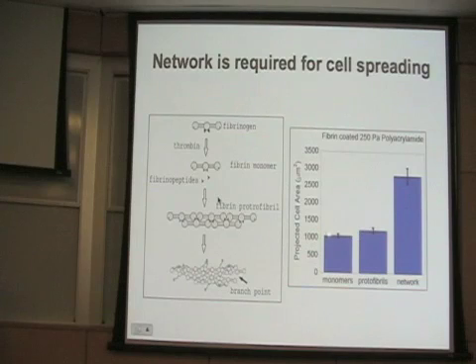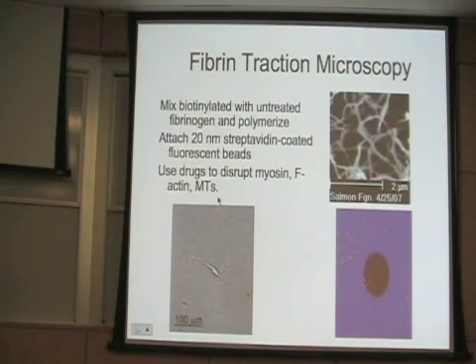Now the chemical information comes from the fibrin, but the mechanical information comes from this linear elastic polyacrylamide gel. So if we put the chemical ligand on an acrylamide gel, if we put either monomers or protofibrils on it, the cells still see it as soft. If we put a three-dimensional network on top of the polyacrylamide gel, they see it as hard. So they're somehow engaging this three-dimensionality. And this also has some consequences in the kind of long-range mechanical sensing that cells might do if you put them on a nonlinear elastic material, which is its normal environment in the body, compared to an elastic material.